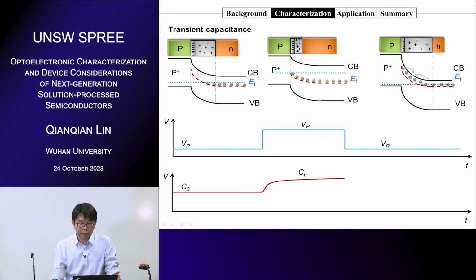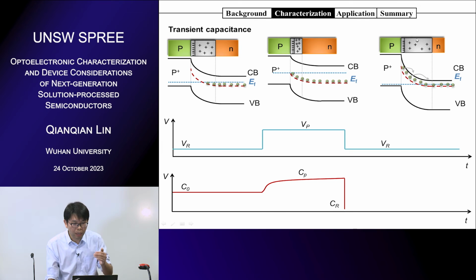The carriers trapped by the trap states will not be emitted immediately. It takes time, and it is also dependent on temperature. The carriers trapped by the trap states will go out to the Fermi level slowly, and the capacitance we measure from the device is even lower than the initial value, because all the carriers are trapped by the trap states and not moving. That's why we have a lower carrier density in the region, and you will have a wider space charge region and a lower capacitance.